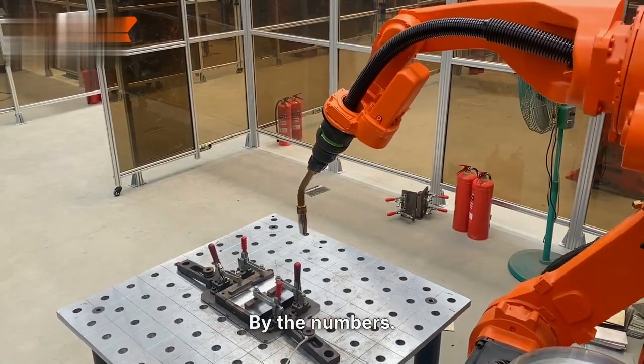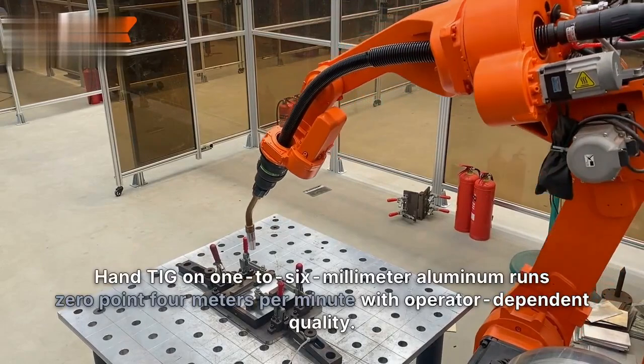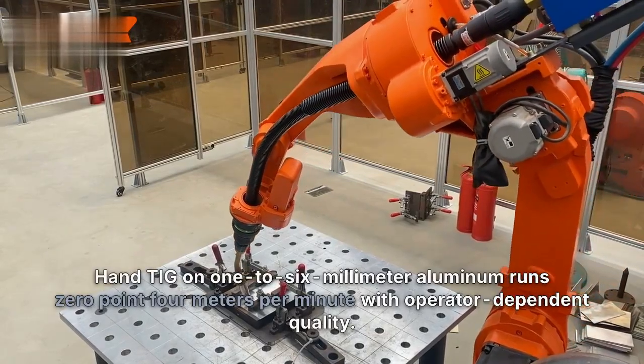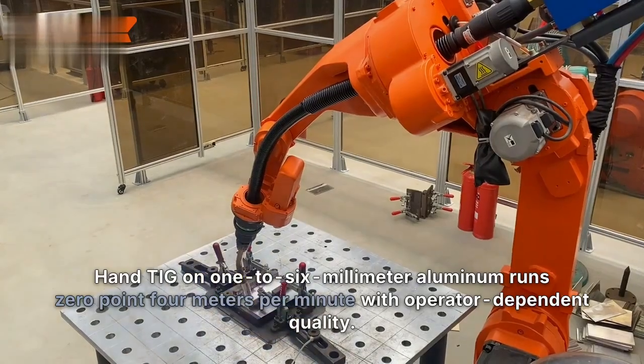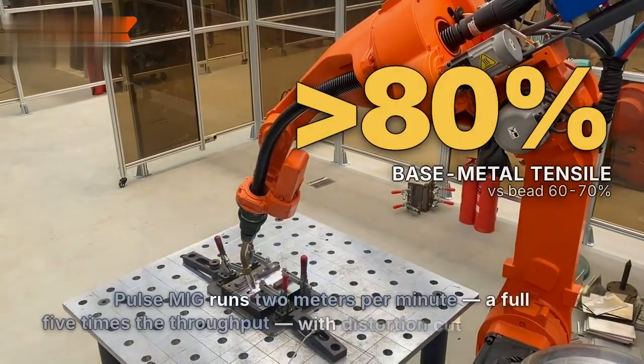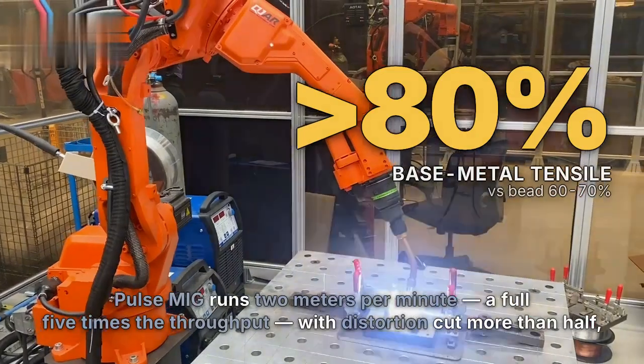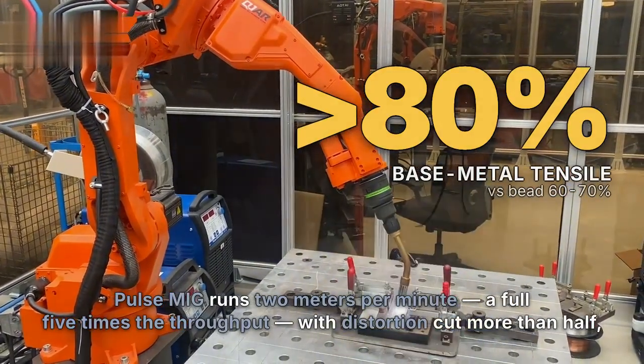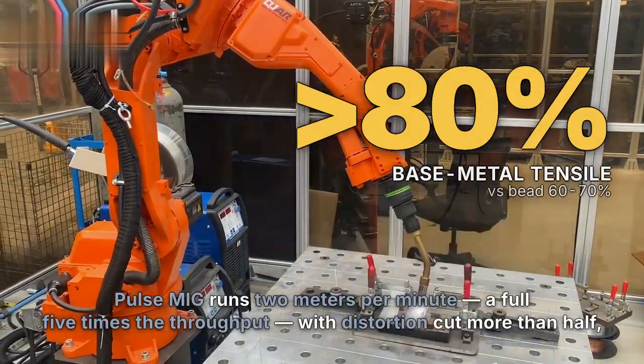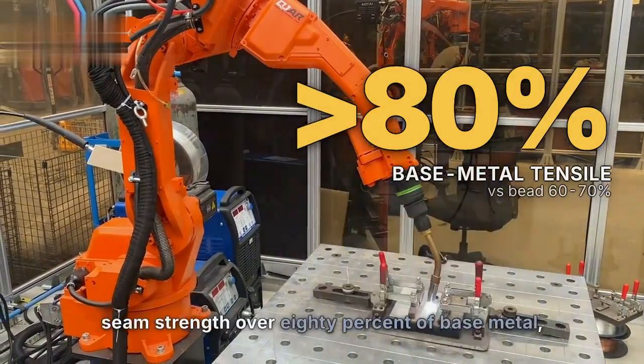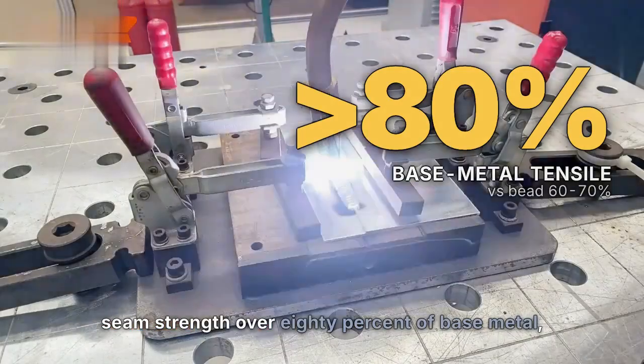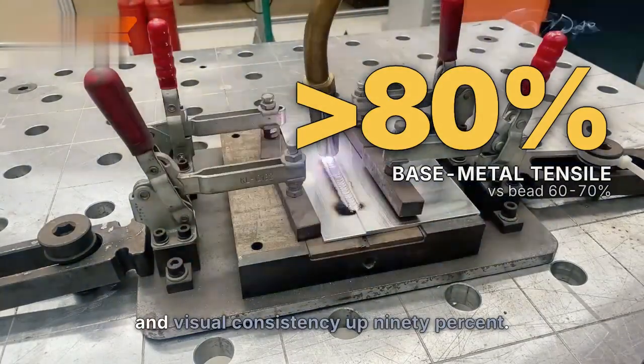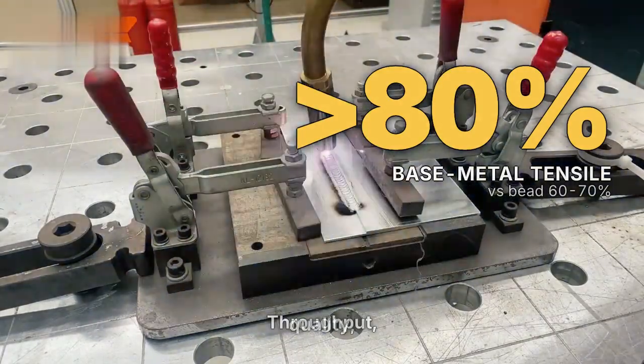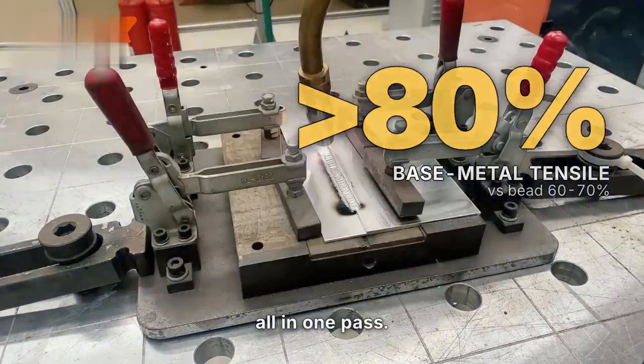By the numbers, hand TIG on 1 to 6 mm aluminum runs 0.4 meters per minute with operator-dependent quality. Pulse MIG runs 2 meters per minute, a full 5 times the throughput, with distortion cut more than half, seam strength over 80% of base metal, and visual consistency up 90%. Throughput, quality, and traceability all in one pass.